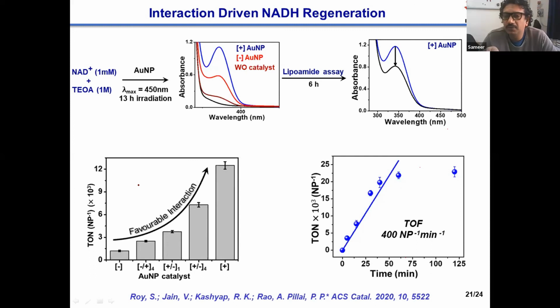Because we did something with just gold nanoparticles, and what we actually found was that it depends on the absorption cross section, how much we can absorb, and it also depends on per gold atom. So when you compare across different sizes, it just gets normalized to the number of gold atoms. The number of gold atoms is actually key; here it may be just the number of ligands. Maybe. I think it's an interesting point. I will check that. If we have only worked with one size of nanoparticle here, maybe it is a good thing to check the size effect and try to normalize it with respect to ligands.